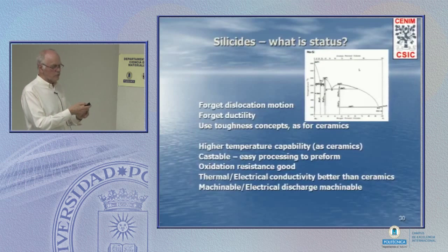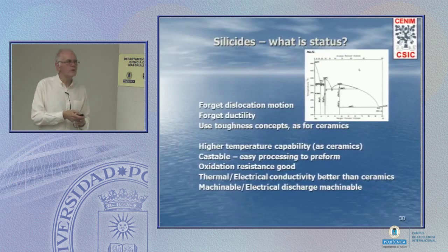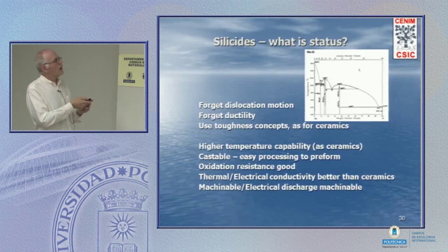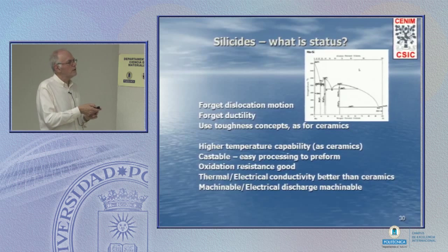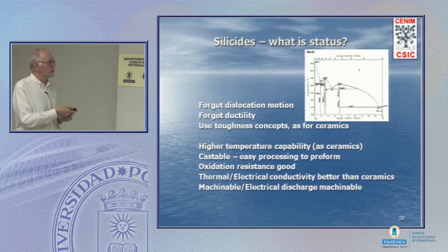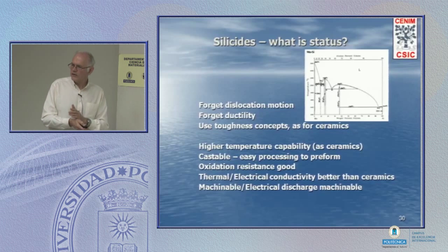Okay, let me jump to another family, the second family I want to look at, the silicides. This is the molybdenum silicon phase diagram, and we've seen before we have a couple of these Daltonide compounds, very strongly ordered intermetallics. Peierls stresses are so high, dislocations are not going to move. Don't bother about the word ductility. You need to use the toughness concept as you do for ceramics. They don't deform plastically, but they are metallic, so they've got high thermal and electrical conductivity.